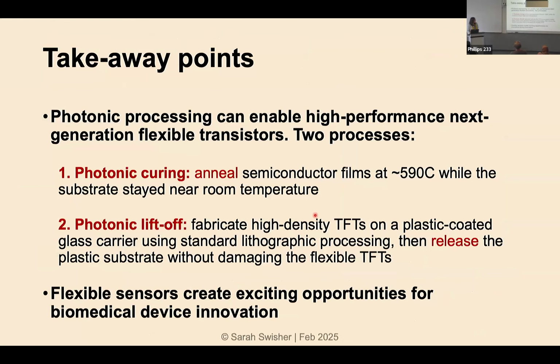So the takeaway points that I want you to get from this seminar, I hope, is that we have this photonic processing that we can use to cure and anneal materials. Here I'm showing it for oxides. But really, as long as you have the absorber layer and you've tailored the material underneath, you could use this for whatever material you want. And then the liftoff process is something that gives us the ability to make nice flexible devices. And those sensors are creating a lot of exciting opportunities for different biomedical device areas.